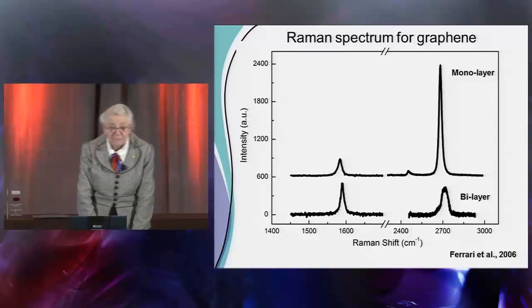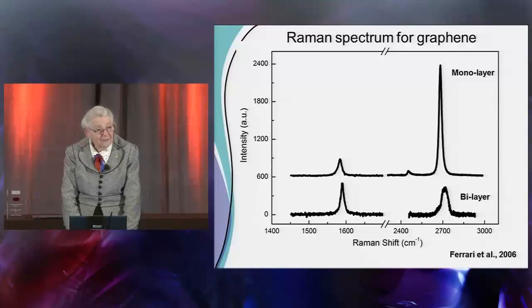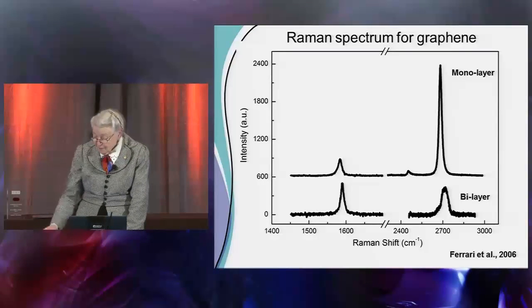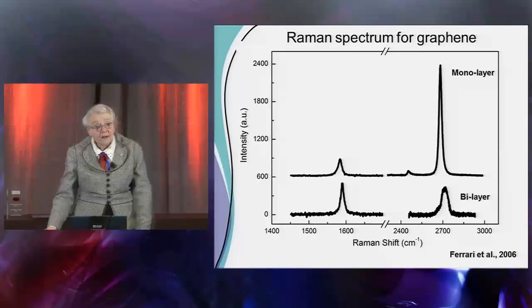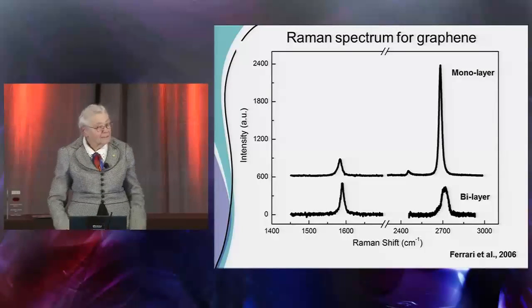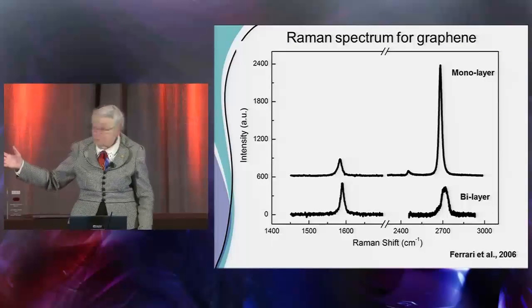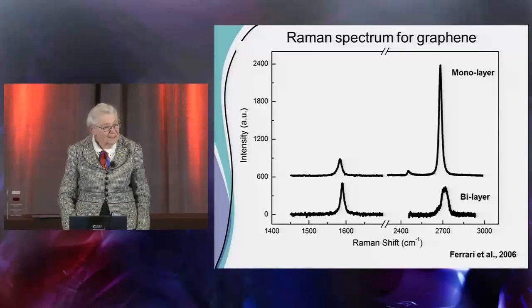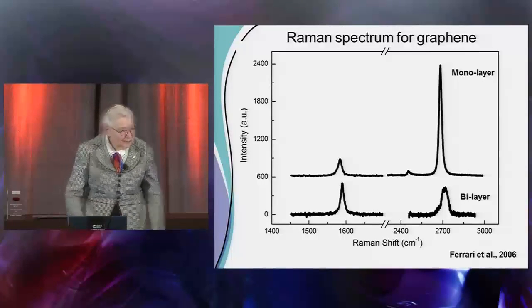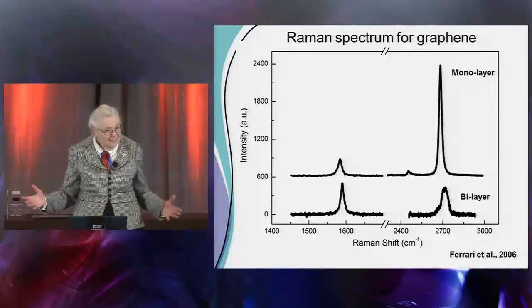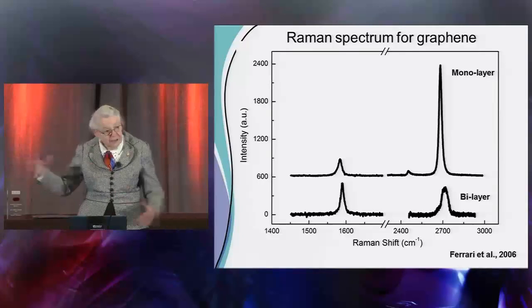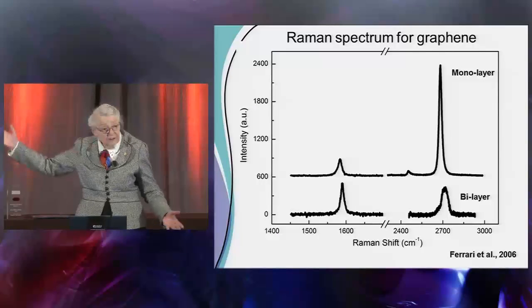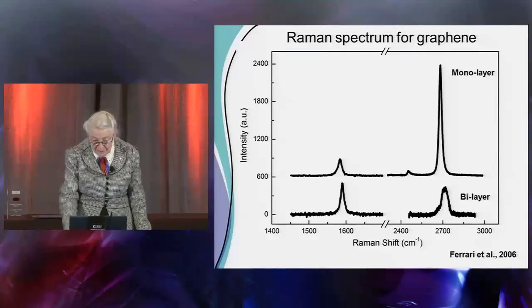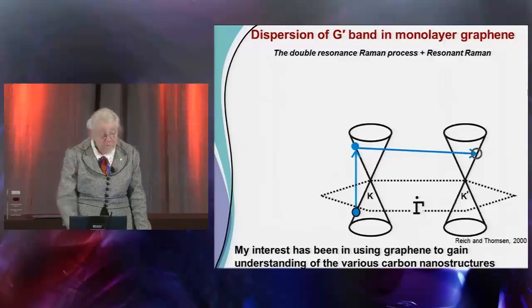Now, in terms of spectroscopy, the spectra are really unique. That is, monolayer has a triple resonance. Everything about this effect is very resonant, and that's why the second-order effect, usually when we do perturbation theory, second-order effects are smaller than first-order effects. But if everything is resonant, and in this case, the scattering is back and forth, so you have a triple resonance, you can get a huge enhancement factor. So that makes the system kind of interesting and gives you a calibration point of when you have isolated layers and when you don't.